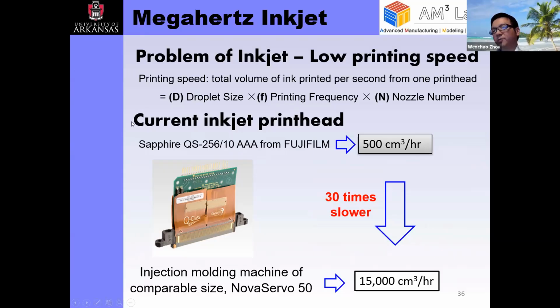Looking at the current inkjet printer here, this is an industrial inkjet printer from Fujifilm, and you can print at a deposition rate of about 500 cubic centimeters per hour. For a similar size injection molding machine, you can inject out 15,000 cubic centimeters per hour. This is an apple-to-apple comparison for making similar things with comparable budget. You can notice that the inkjet is 30 times or 100 times slower than injection molding machines. This means if we want to be able to compete with traditional manufacturing, we need to at least bring up the printing speed by 100 times. This is one of the motivations for our project.